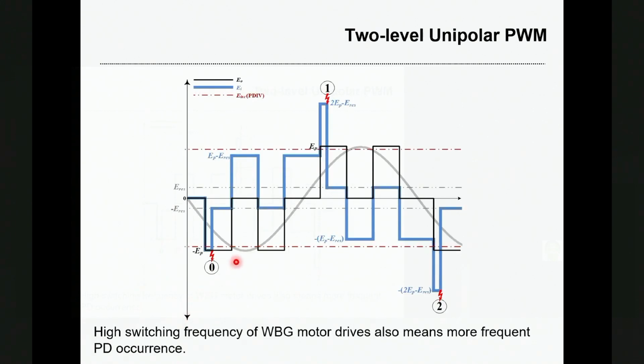And similarly, you can use this field change diagram to analyze a two-level waveform, switch waveform, where this black one shows. And the PD normally happens when you change the polarity of the voltage, for example, from the negative to the positive, or from the positive to the negative. It will have the PD events. And also the high switching frequency of wide-bandgap motor drives also means more frequent PD occurrence, because you have more pulses within a certain time under high switching frequencies.